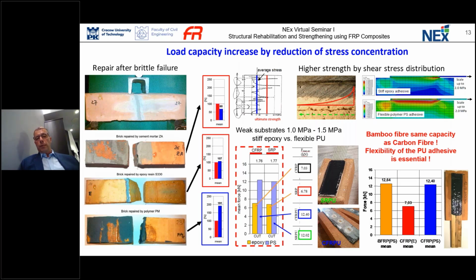But what is very tricky, when we did directly the same test on the same brick, the same system, the same setup, but instead of epoxy resin, where we had 7 kilonewtons for carbon fiber, when we used the flexible polyurethane adhesive, we received 12 kilonewtons. But when we replaced the carbon fiber with grass, I mean bamboo fiber, we directly received the same ultimate load value. So this is simple proof that the key point in bonding is the adhesive, not the strong carbon fiber or other strong composite material.